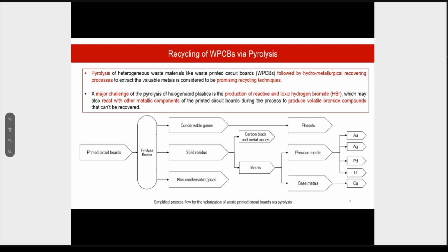So one of the other techniques that I'm proposing or using in my PhD actually is pyrolysis. Pyrolysis in general is a thermal degradation of organic material, that can be polymers, into different value products like condensable gases, non-condensable gases, and carbon black. So using the same process for electronic waste has many advantages since it's a low temperature process. We avoid melting most of our metals compared to the smelters.